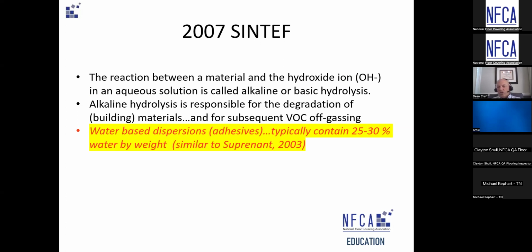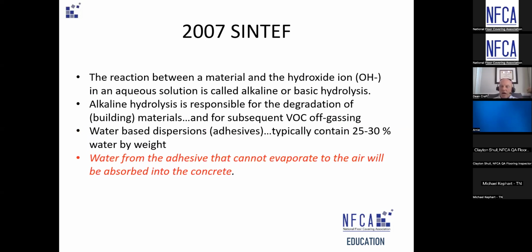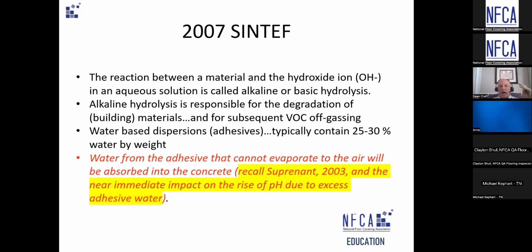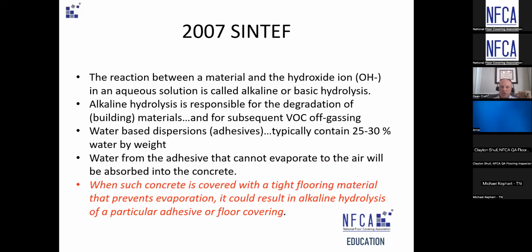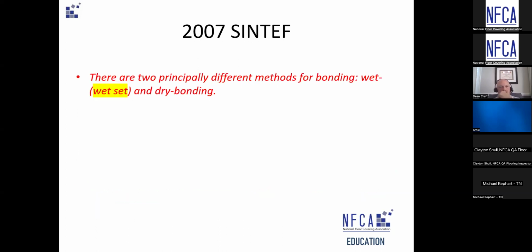Now, what they also noticed was just how much liquid is in some of these water-based adhesives, 25 to 30%. I know a lot of our adhesives today are much lower. Again, I'm giving you a historical perspective of where pH testing came from. A lot of these failures could be attributed to misapplication of an adhesive that had a lot of water, went on a non-porous substrate, wasn't allowed to evaporate, and was covered with a floor covering too fast. If it didn't have anywhere to go, it's going to cause those alkalis that are dry and silent and behaving themselves in the concrete to go into solution and cause mischief. Then you cover with flooring, and the adhesive itself is now the culprit that's attacking itself. So anyway, there we go.